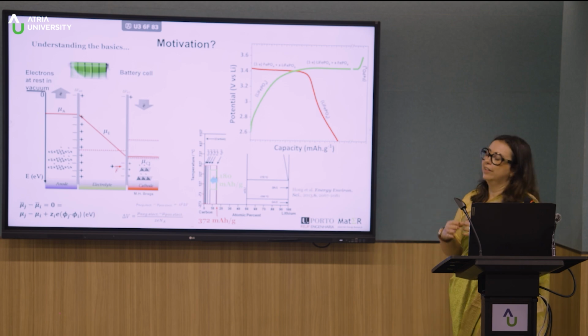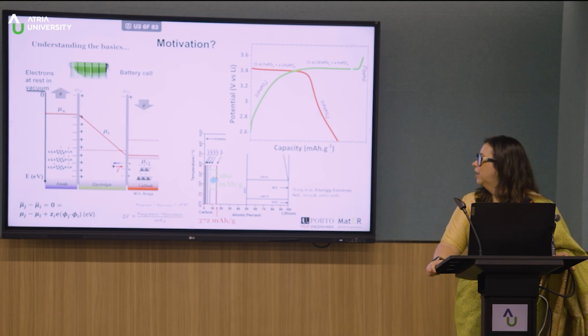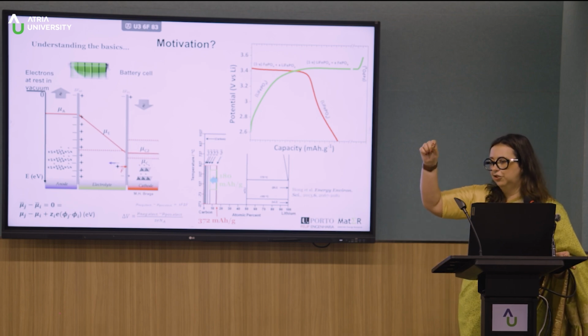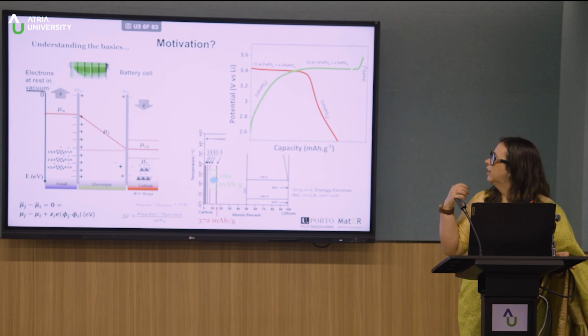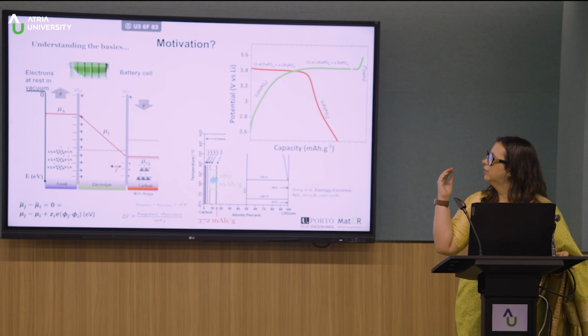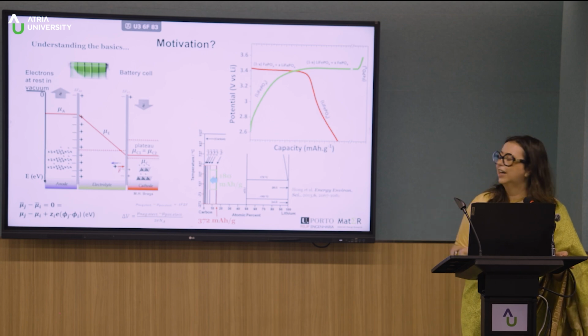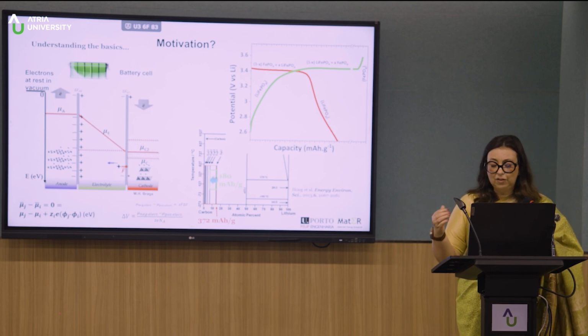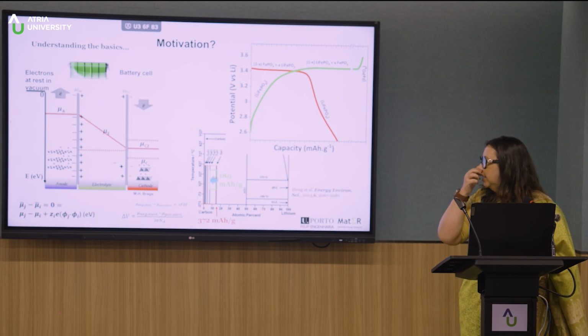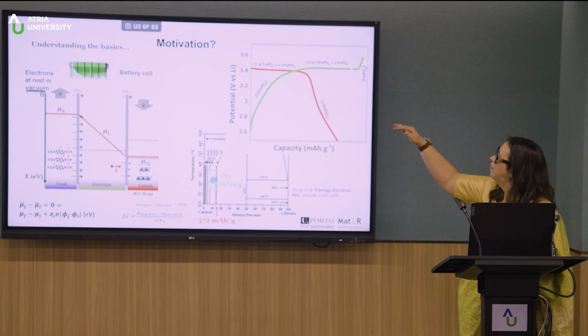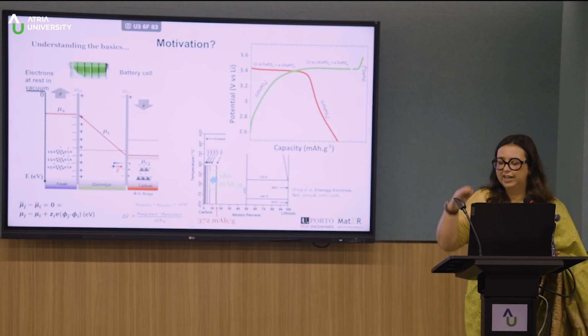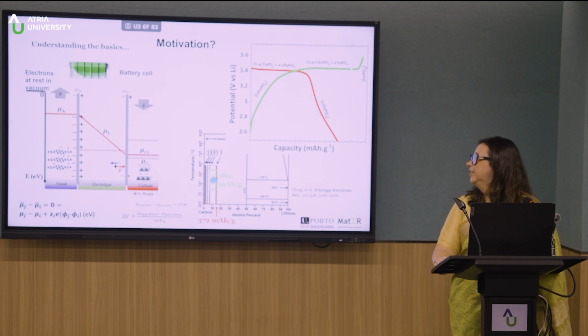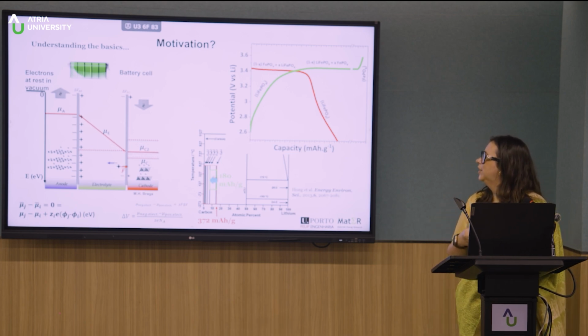But there are many other batteries, like NMC, for example, in which you don't have this plateau. You have a solid solution, and you use lithium while you are charging. The lithium goes from the cathode, actually from the positive electrode, to the negative electrode, and while you are discharging, the other way around. But it's a solid solution, so you don't have a perfect plateau, you have like a slope. Why do we need to know this?